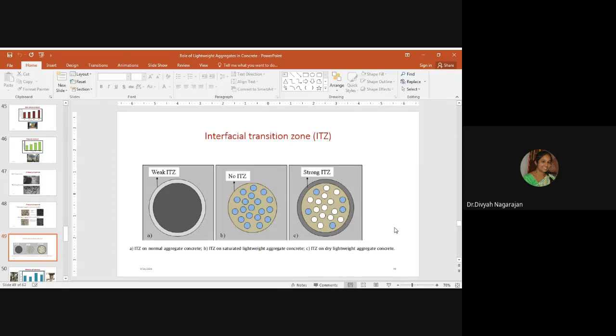During the initial stages, the ITZ generally has a higher water to cement ratio, and the interparticle spacing compared to the bulk paste is higher. Lack of proper curing at early stages may result in imbibing water from the pores within the interfacial transition zone. This creates large pores near the zone.